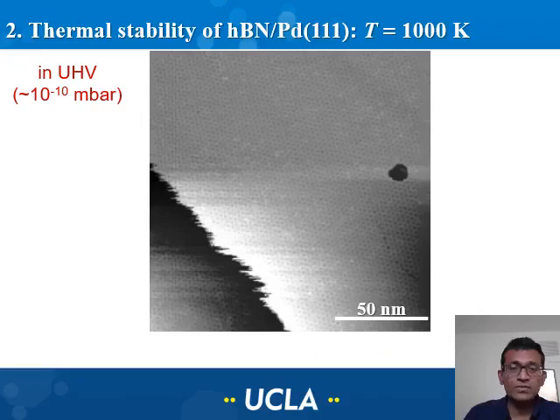changes. Let me focus in particular on this when we did the same experiment in ultra-high vacuum. What you're going to be looking at is the changes in the corrugation of this single atom height step and fluctuations in the shape of this vacancy island. These dots that you see are a moire pattern that develops because this entire surface is covered by a hexagonal boron nitride layer. So this is a palladium surface covered with a monolayer of hexagonal boron nitride. And you may also have noticed these slightly different contrast dots,